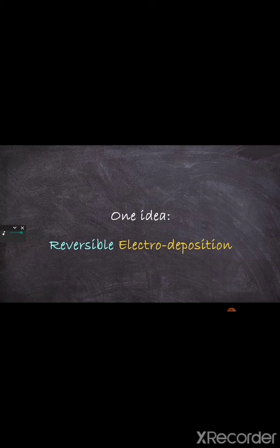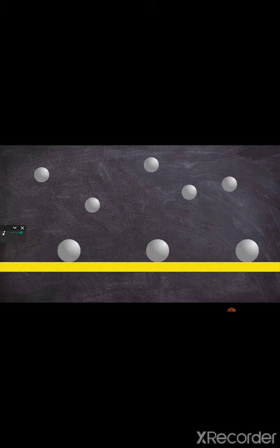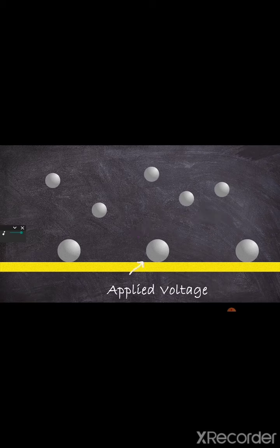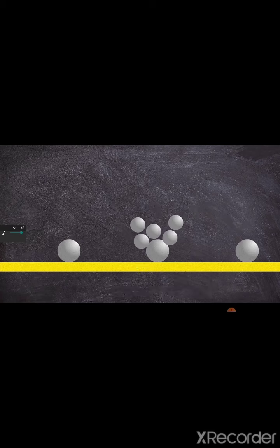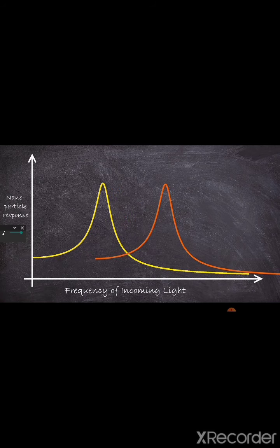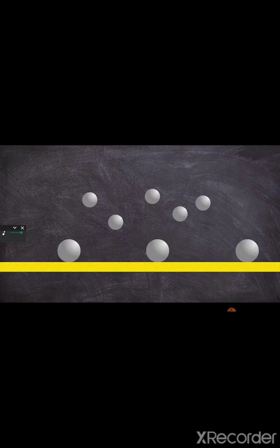One example is to use the voltage to literally control the reversible deposition of silver onto a silver nanoparticle. In other words, your silver nanoparticle is embedded in like a gel containing silver atoms, and by using a voltage, you can tease those silver atoms to deposit on the surface of the nanoparticle. As a result, the nanoparticle basically just gets bigger, and its plasmonic resonance then shifts. If this deposition is reversible, you can then undo this accumulation by reversing the voltage.